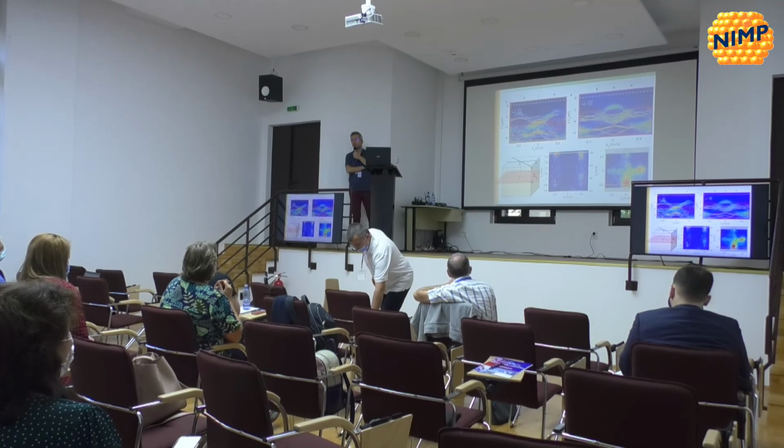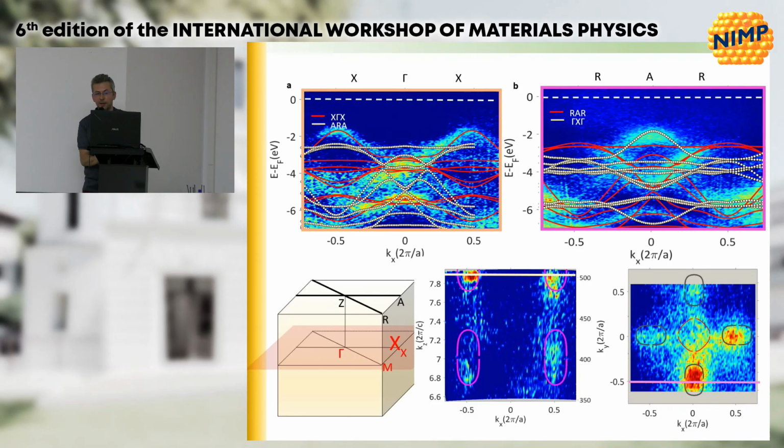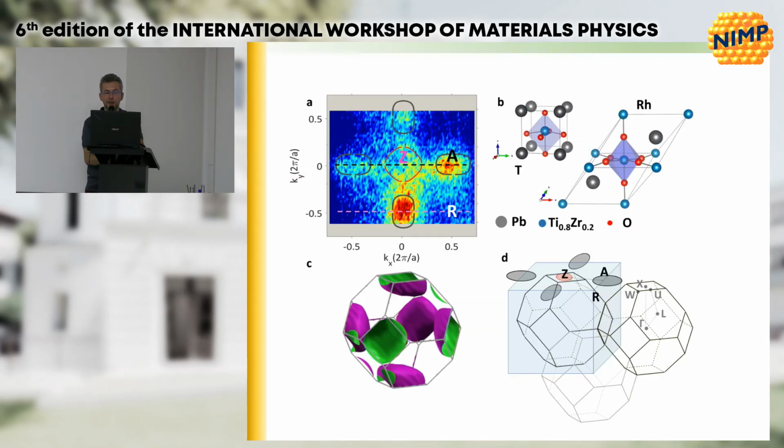Historically, we tried to interpret our data only with the band structure of the tetragonal cell. And we see that assuming a perfectly tetragonal unit cell, we would expect only this point and not these additional features. So that's from symmetry analysis alone, or from first principles data? From first principles.